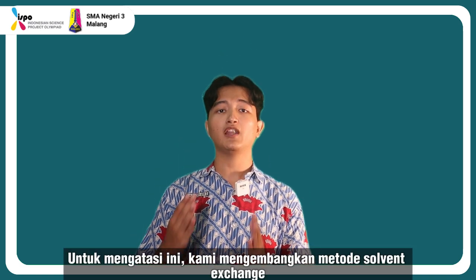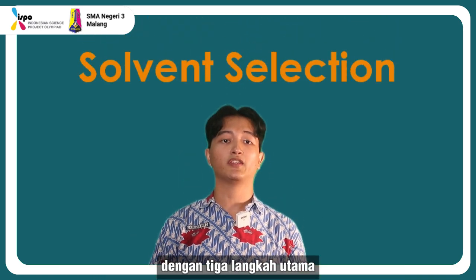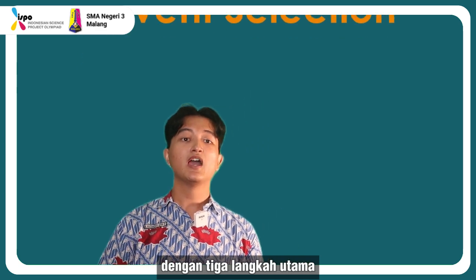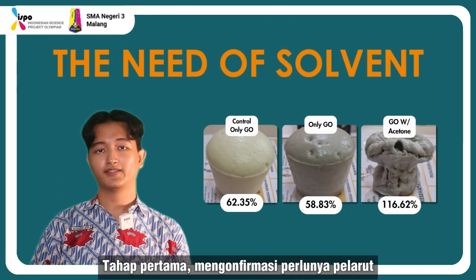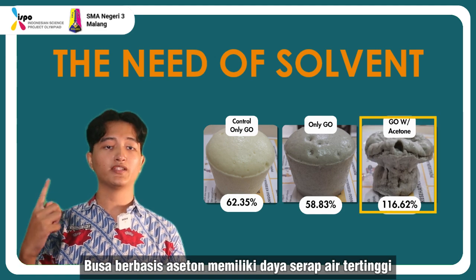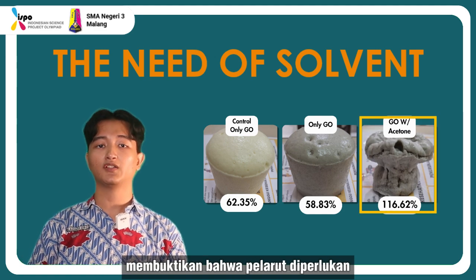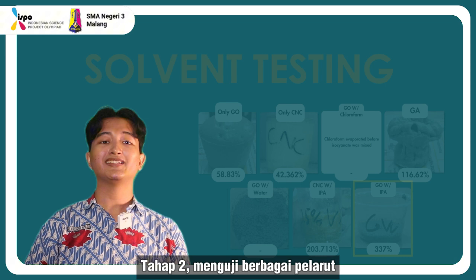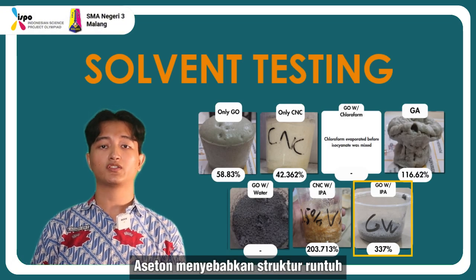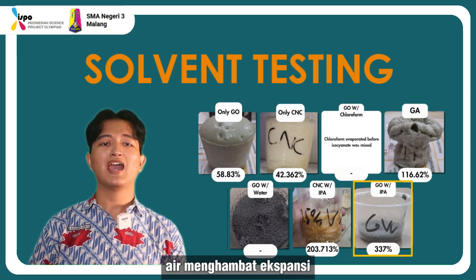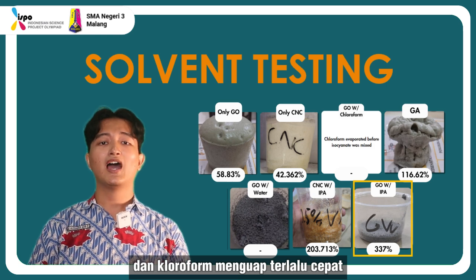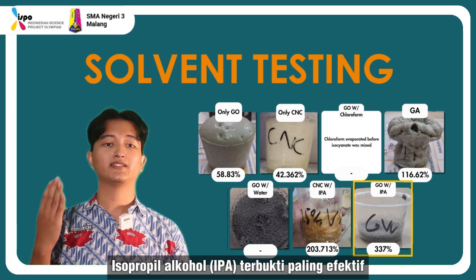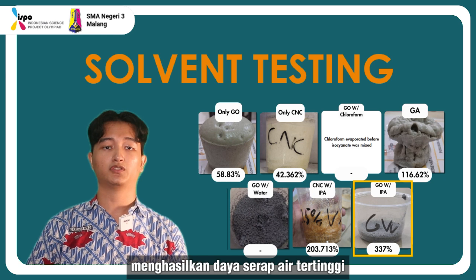To solve this, we developed a novel solvent exchange method with the thought process of these 3 steps. Step 1, confirming the need for a solvent. Acetone-based foam showed the highest water absorption, proving a solvent is necessary. Step 2, testing different solvents. Acetone caused structural collapse, water prevented expansion, and chloroform evaporated too quickly. Isopropyl alcohol, or IPA, was the most effective, yielding the highest water absorption.